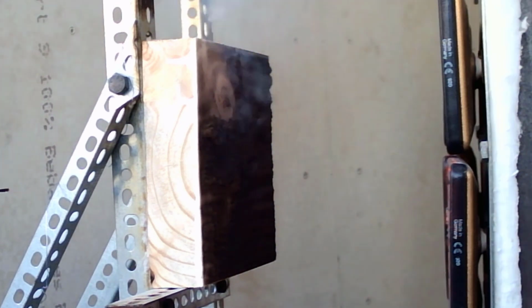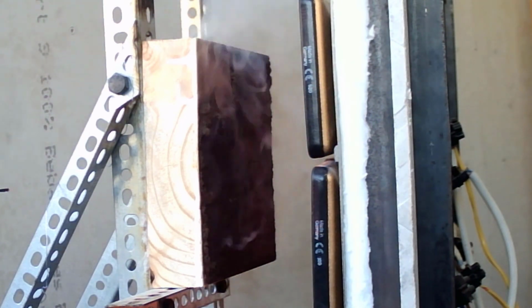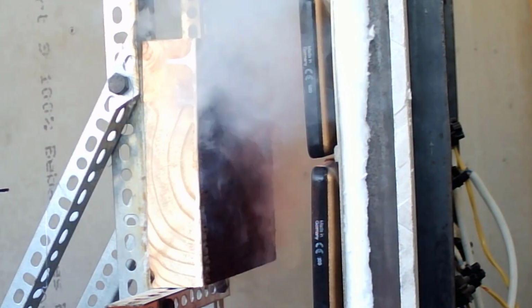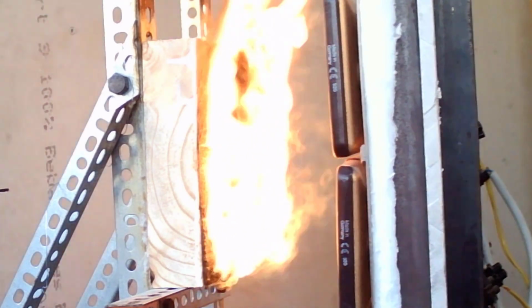Here's the timber with the intumescent paint on top being tested. Now, this paint product is still under development, and you'll see it's not fully effective. It does swell a bit, but not enough to actually protect the timber. And what eventually happens when we move the radiant panels closer is that the sample actually ignites and you have flaming across the surface. So this needs to intumesce much more to provide a thicker protective layer to the timber.